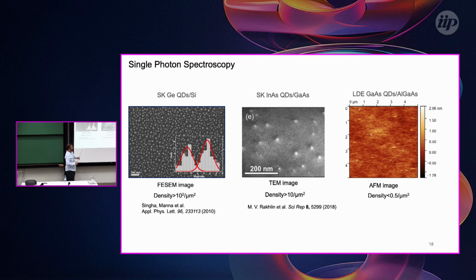This is the nanoholes, but it's how I count these quantum dots when I grow some test samples. If you compare to the Stranski-Krastanov indium arsenide, this is, let's say, 1 micron by 1 micron, and you have almost more dots than the gallium arsenide quantum dots. And you see the density is very high. For single photon sources, when you want to isolate a quantum dot, it's much better if you have a very low density like the gallium arsenide quantum dots.